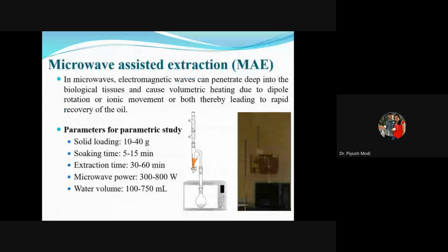Next we studied microwave-assisted extraction. It is again a small setup available in our lab. The solid loading is 10 to 40 gram, soaking time 5 to 15 minutes only, and extraction time 30 to 60 minutes. I studied half an hour to 1 hour of extraction time on the plant material, and the microwave power is 300 to 800 watt. The volume of water is 100 to 750 ml.